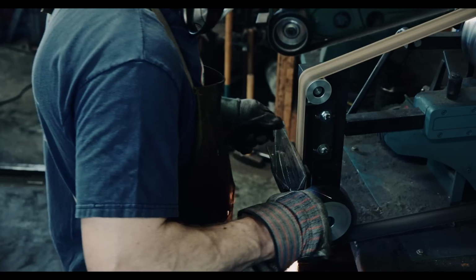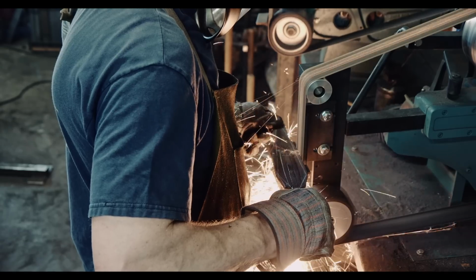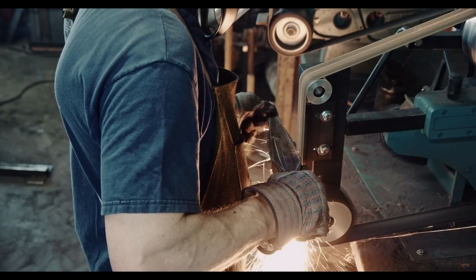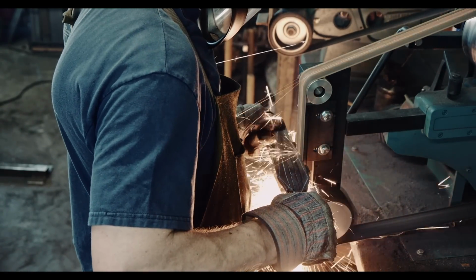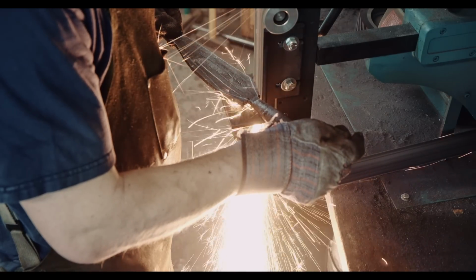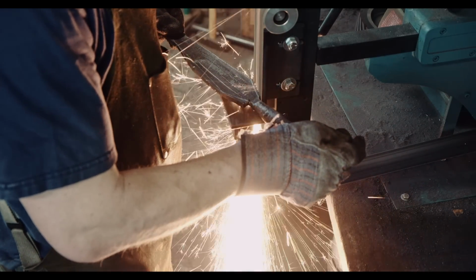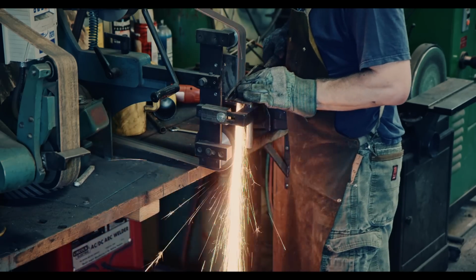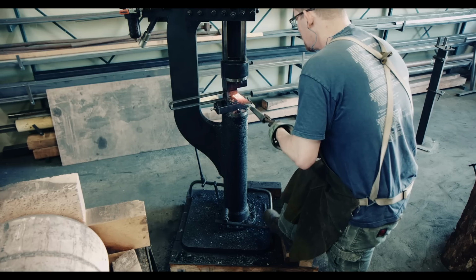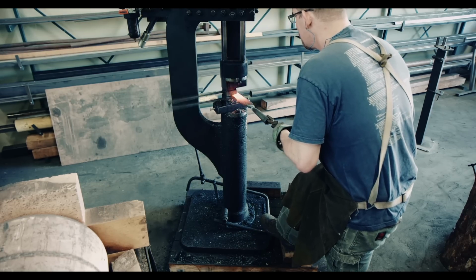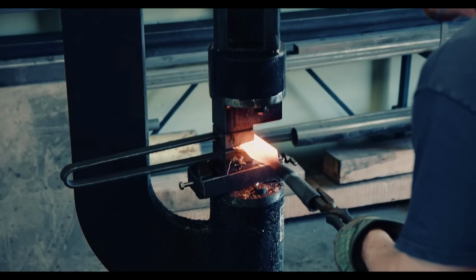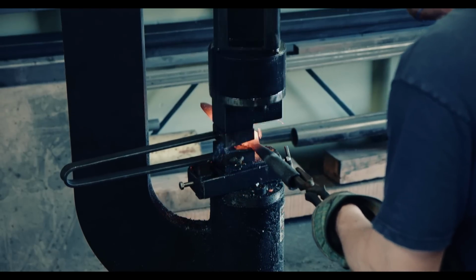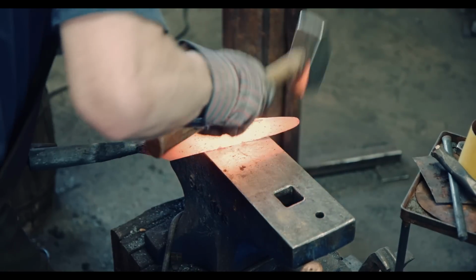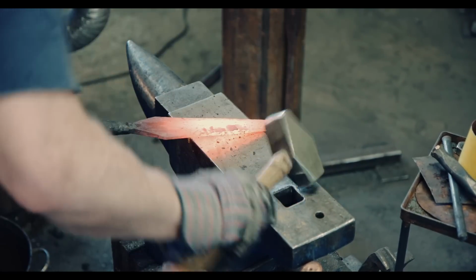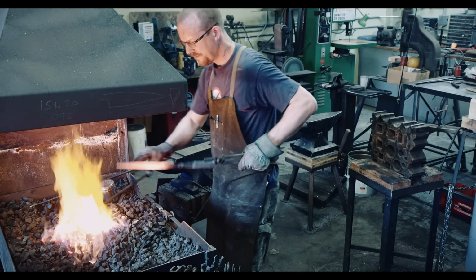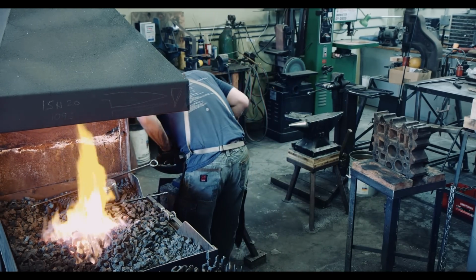The grinding you are seeing here is also good for removing any of the remaining tack welds. I am now removing the scale, covering many of the forge welding steps, so that I can see if everything has come together correctly. There are a couple remaining forging steps, and one of them is to establish the edge bevels. Another challenge is to avoid distorting any of the pattern welding, so there are many iterative adjustments to make sure that the edge lines flow smoothly and that everything remains centered.